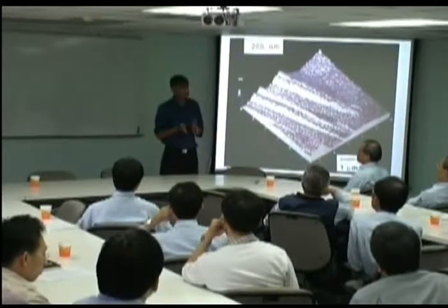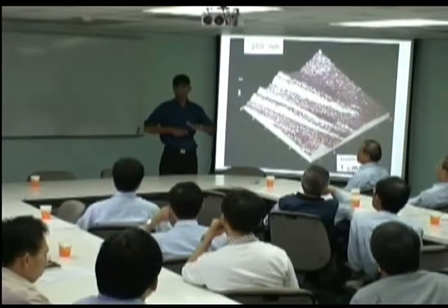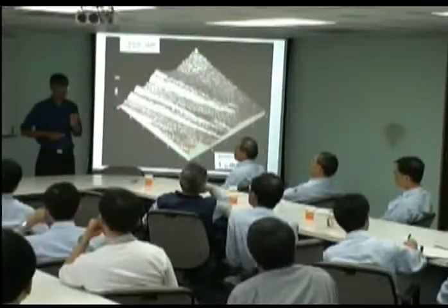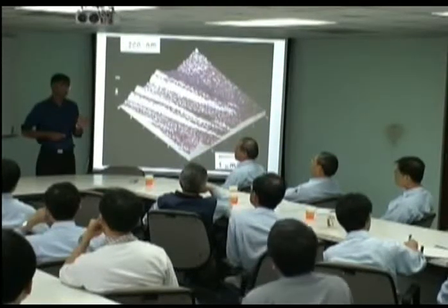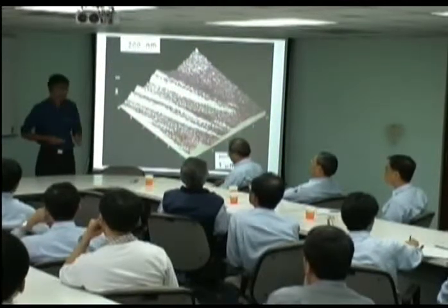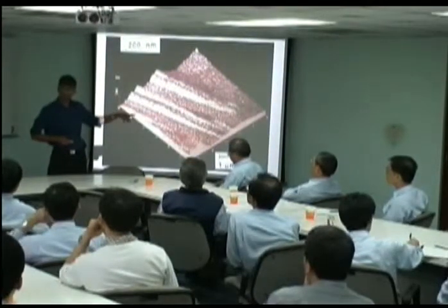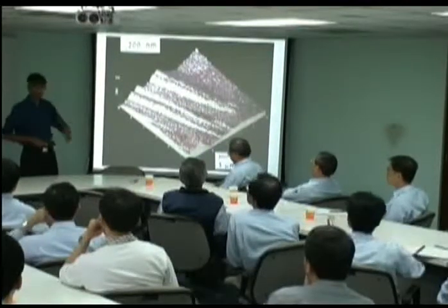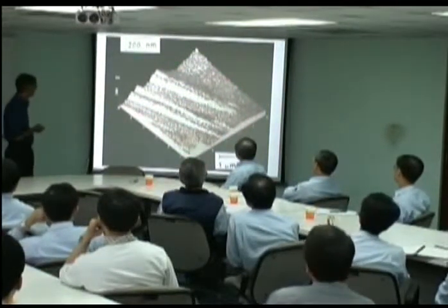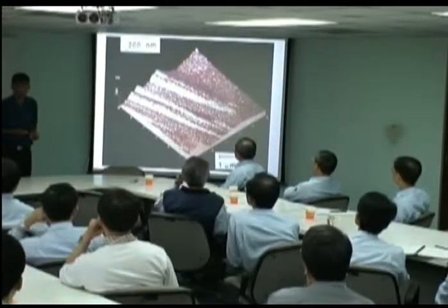So the shape deformation of martensite has been established for a very long time, because you can do it using optical interference microscopy. With bainite, that's much more difficult because you are close to the resolution limit of light. Light has a wavelength of about half a micrometer, and you are trying to resolve 0.2 of a micrometer. So this is not taken using an optical micrograph, but using an atomic force microscope, which looks at surface topography. So this is austenite transformed to plates of bainite, and you can see the enormous shear, which you can measure quantitatively, and it's about 0.26.